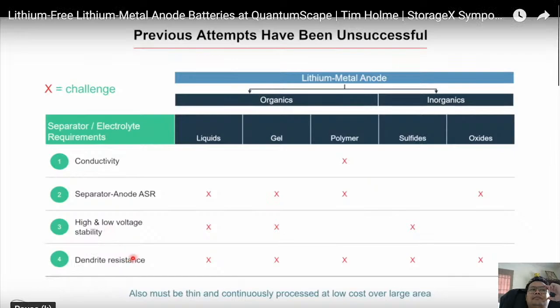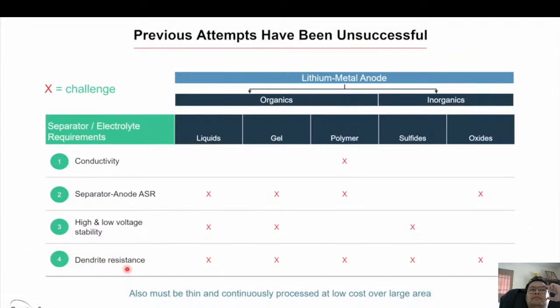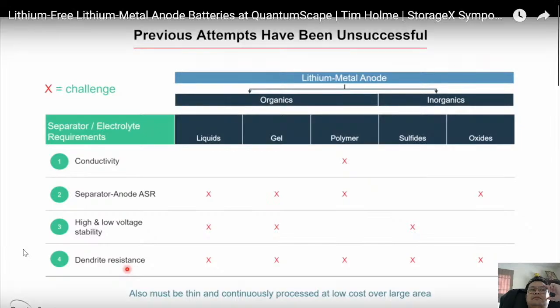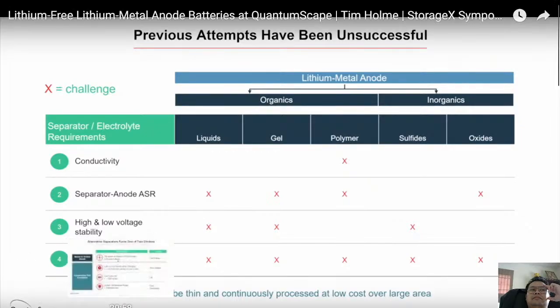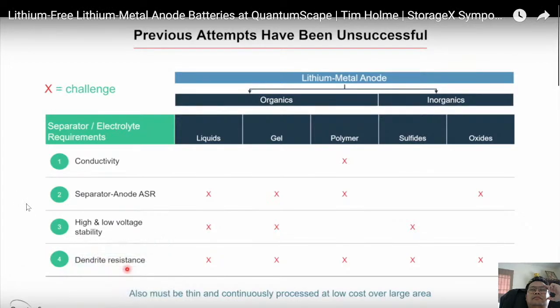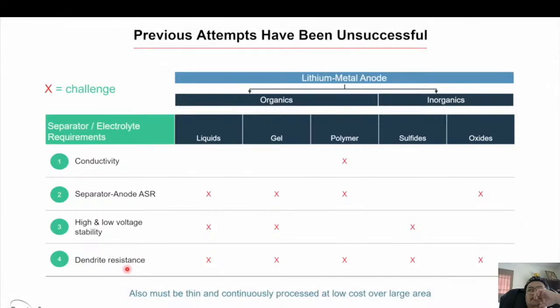And then, of course, dendrite resistance is probably the biggest challenge here. So as described earlier, when lithium plates on the anode, it tends to form these dendritic structures that bridge across to the cathode and result in an internal short circuit. Dendrites tend to form exponentially more aggressively as you increase the current density during charge. So as you go to a fast charge requirement, it becomes very difficult. And I'm not aware of any really compelling demonstration that a cell can resist dendrites over many cycles and realistic automotive conditions. So that's a big challenge.